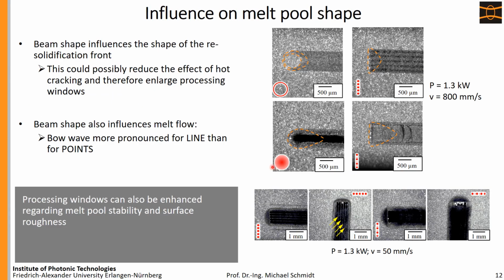So looking here, what's the influence of the different intensity distributions on the molten pool shape? You can see it here, and we tried also in the orange dotted line to show you how the solidification front looks like. And you can see that depending on the intensity distribution that you use, we have quite different shapes of the solidification line, which of course influence not only the microstructure but also things like hot cracking susceptibility, for example. And this is shown here.